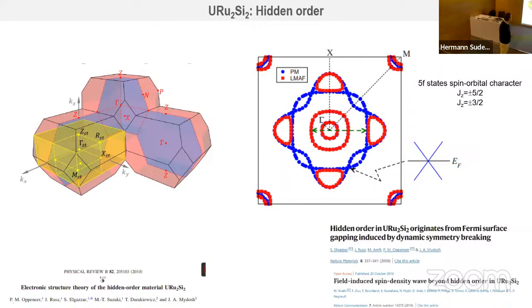Now, the hidden order is actually, we know many things about hidden order. We don't know what orders, but we know many things about it. And one thing which we know is that this is a tetragonal structure, okay? And then when you go below this transition, actually the two uranium sites, which are inside the tetragonal structure, one located to the corners and one at the center, they start to be non-equivalent. Now, the electronic crystalline structure remains exactly the same. There is no structural transition.